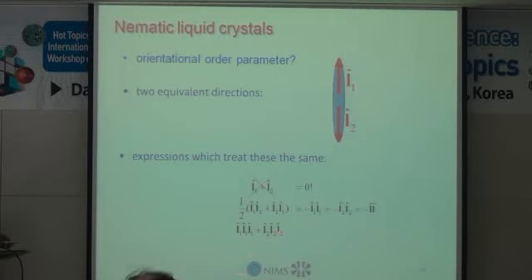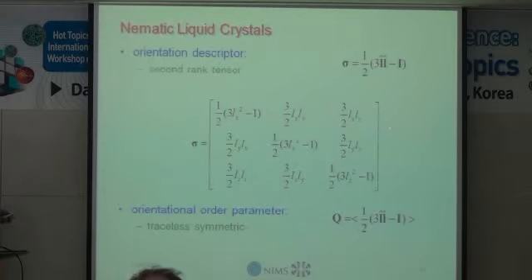One could continue this, but it's simply not necessary. So a good order parameter for an object like this is a dyad made from a unit vector along the symmetry axis. And for the sake of convenience, usually this is normalized and the trace is subtracted out. So the orientation descriptor is this little second-rank tensor made up of the components of a unit vector along the symmetry axis. And the order parameter is just the average value of this.